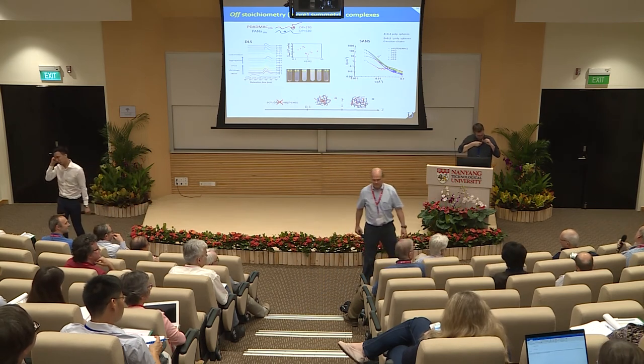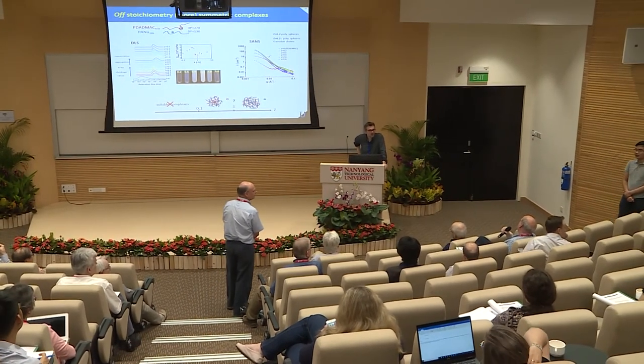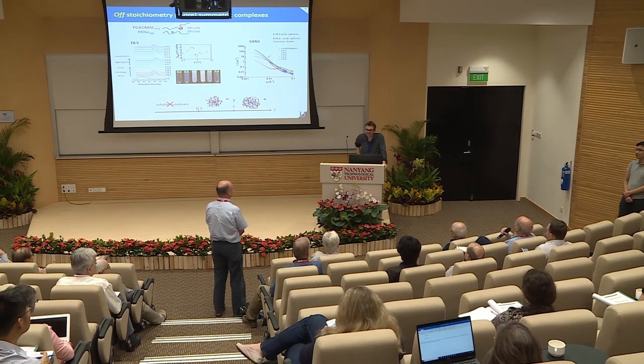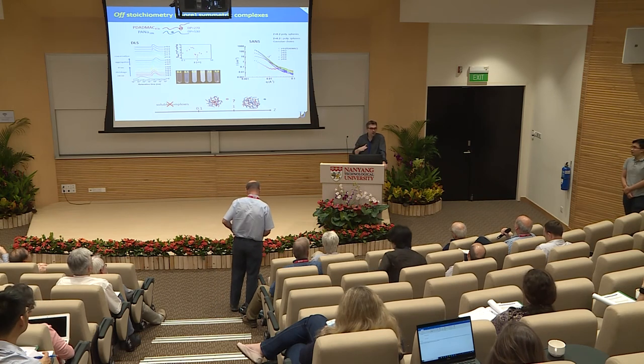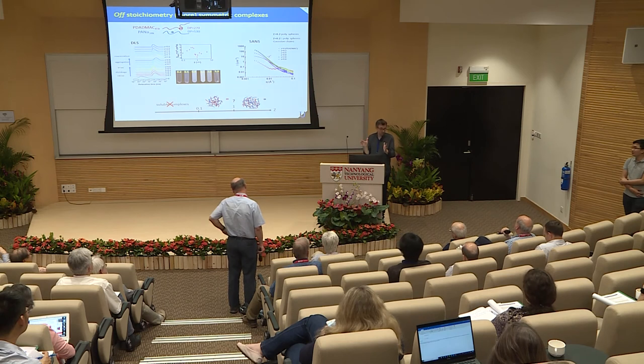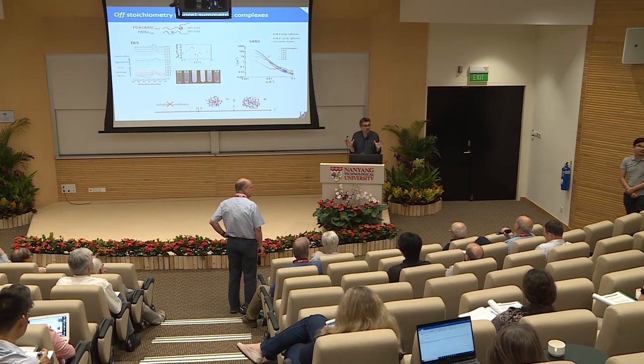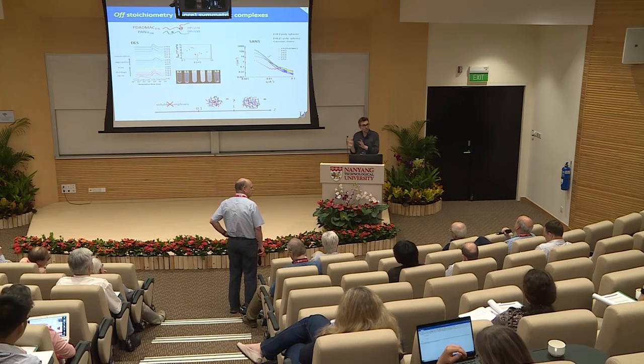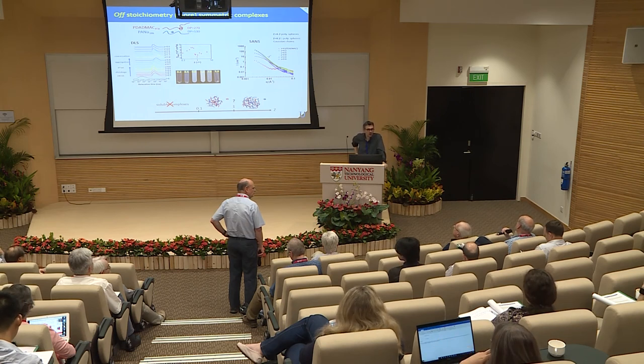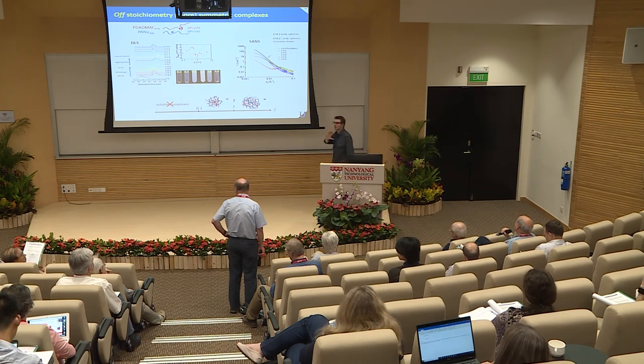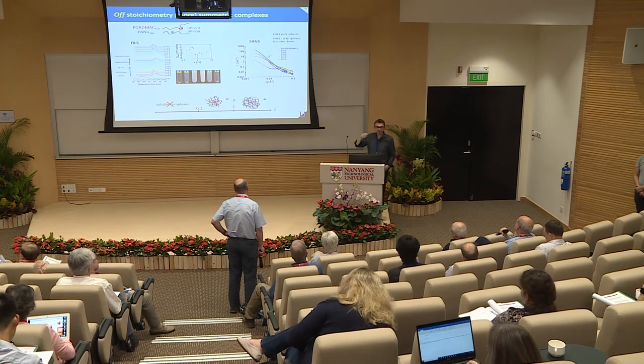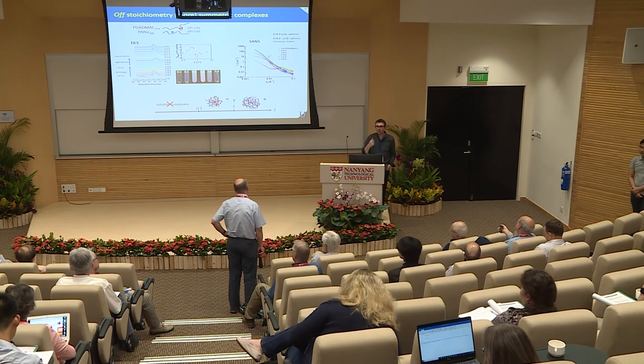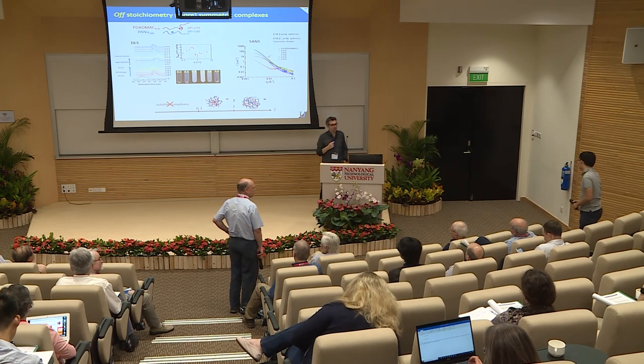Final questions: Was the neutron scattering done in heavy water? Obviously, yes — otherwise it's impossible to get any result. Any effect of replacing light water with heavy water? We did that with light scattering and didn't see any change between water and D2O. A final question about contrast variation to separate contributions from the two polymers — that's what we want to do in the future. We did stop-flow under a SANS beam as well, but the coacervation was too fast to be monitored by SANS. Contrast matching is something we might do one day if we have the funding.